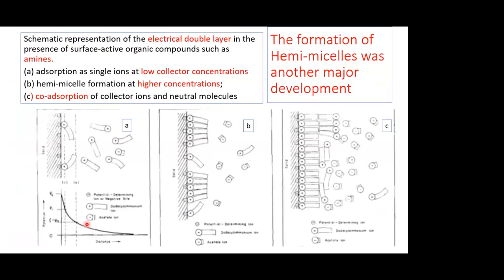So this was the concept of the hemi-micelles. This is a figure which I'm sure you've all seen many times before in your life. On this side here, we see these amines as single ions at low concentrations. Now remember in that figure I showed you, which I said was such a seminal breakthrough, the hemi-micelles really only started happening when the concentration became very high and the coverage was close to one. Here you can see the coverage is probably only about 10% if you just want to use a figure.